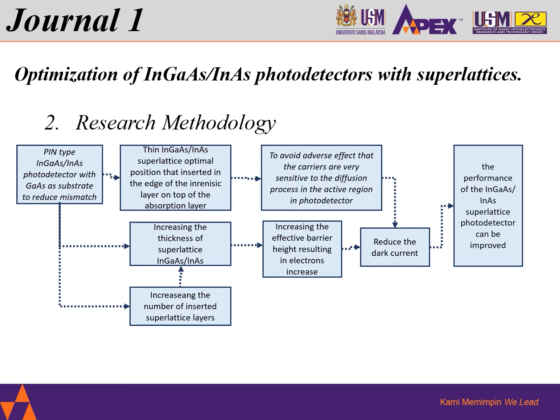And number three method, increasing the number of inserted superlattice layers. To avoid adverse effects, the carriers are very sensitive to the diffusion process in the active region in the photodetector, and finally reduce dark current. Now increasing the effective barrier height, resulting in electrons increase, resulting in reduced dark current. And finally, the performance of the